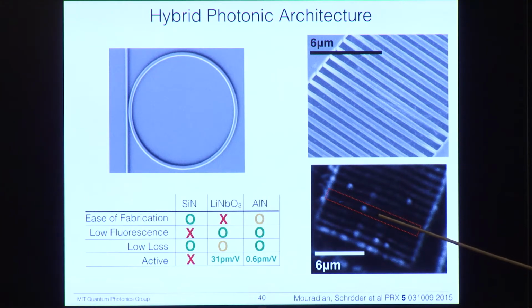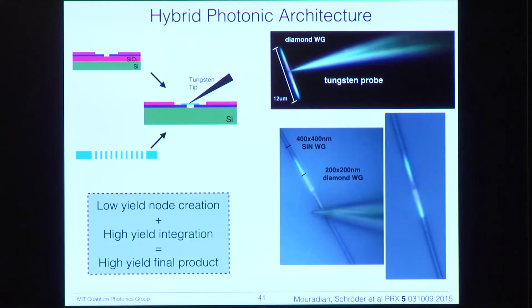So let's say we want this one because it has this nice NV center near the center. So what we do is we pick it out with a tungsten probe. We then bring it over to our nice platform with our silicon nitride waveguide, and we place it down with our tungsten tip. So here it is on the tip. Here's our single mode silicon nitride waveguide, our single mode diamond waveguide, and our tip placing it down.